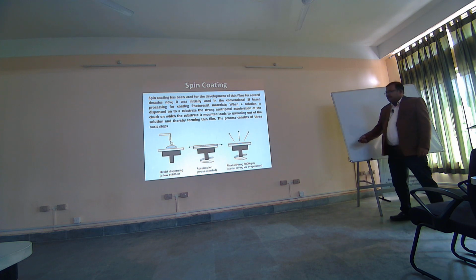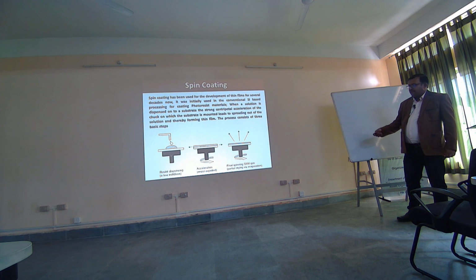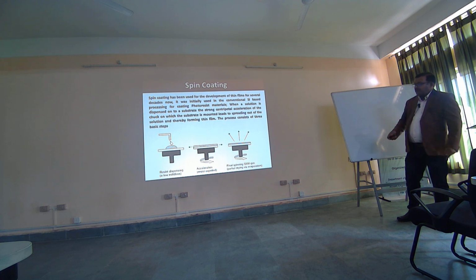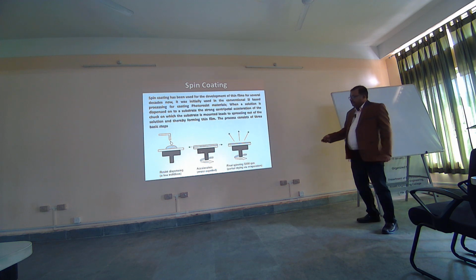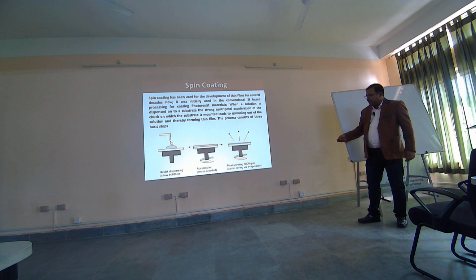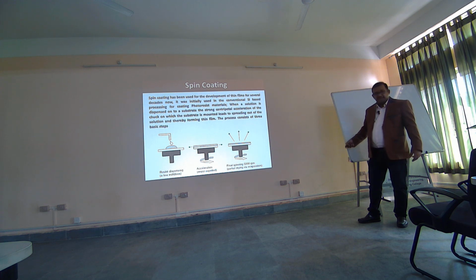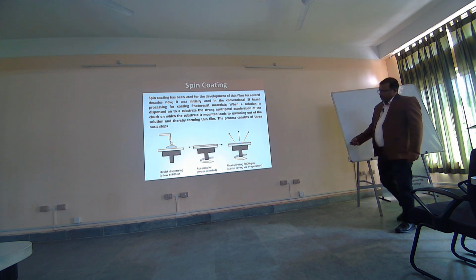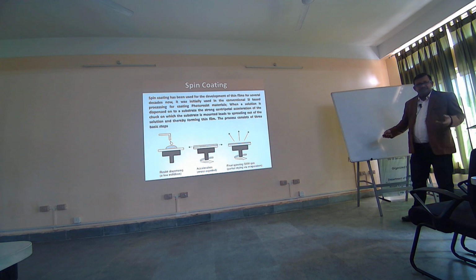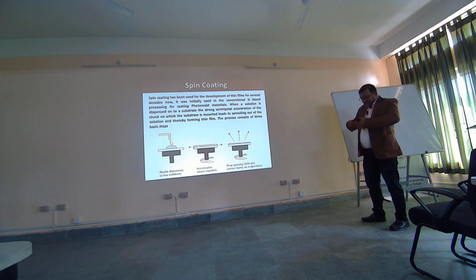So spin coating is typically, you have a vacuum chuck and there is a very fine bore through which it is connected to a pump, and you place your substrate, and when the vacuum pump is switched on, because of the suction, the substrate is held to the chuck. On the substrate you drop your solution, and then you preset some time and some rotation speeds, typically 1000 rpm, 2000 rpm or so, and a certain time, 30 seconds, 40 seconds, like that. And when you suddenly accelerate or rotate it, because of the centrifugal forces, suddenly this entire material